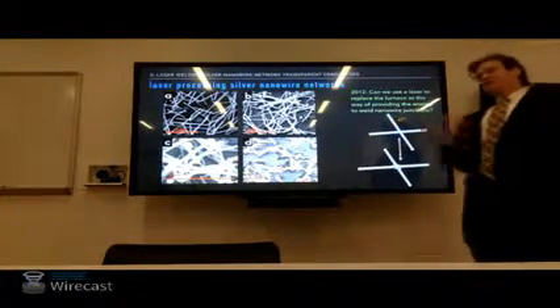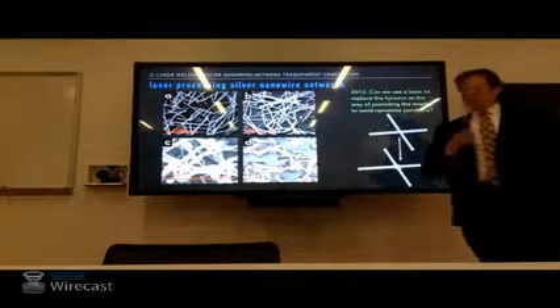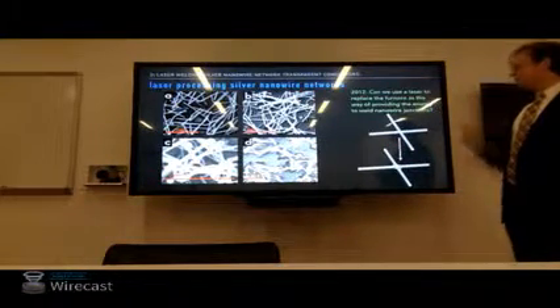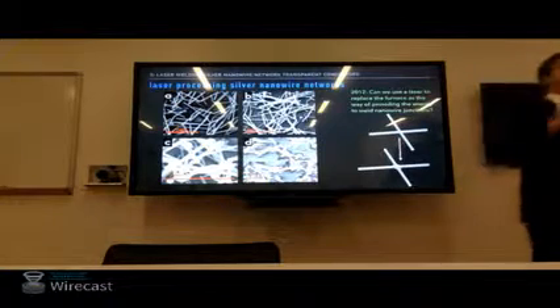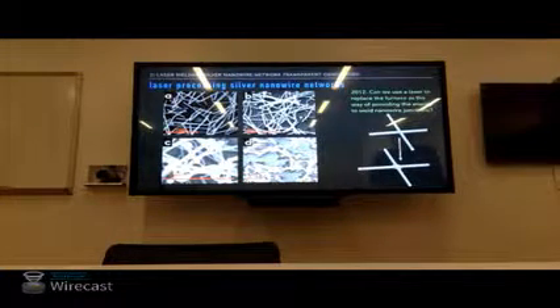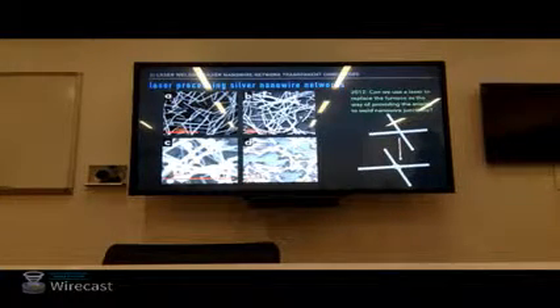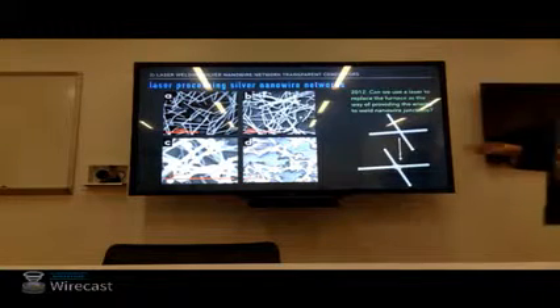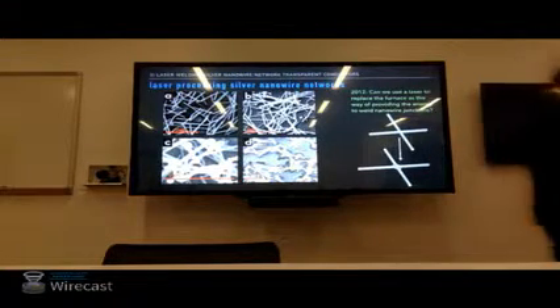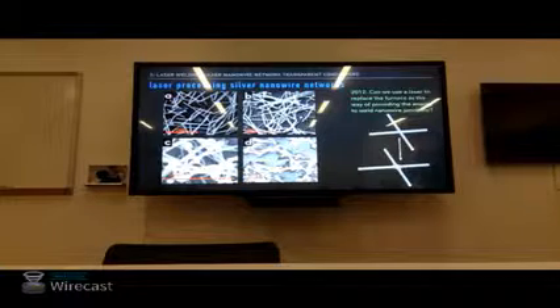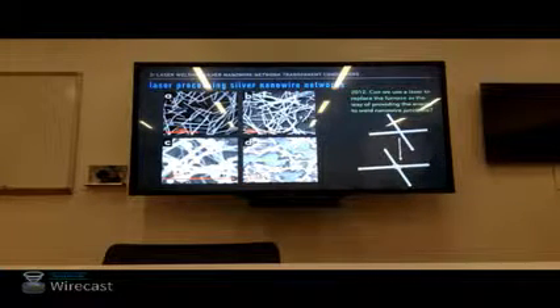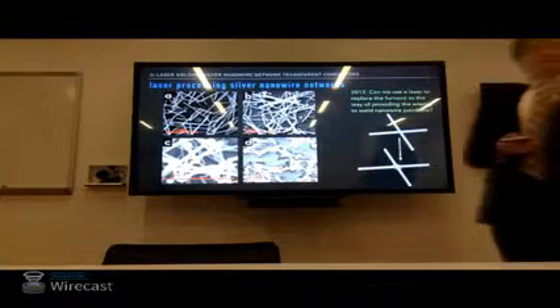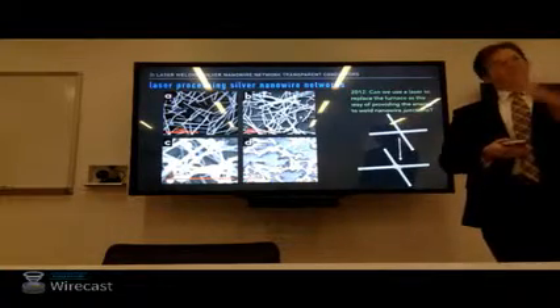The end of a nanowire is also a place where you would expect a lot of scattering, another high curvature. And of course in D, if we increase the laser energy density, or the fluence, much higher, we can definitely destroy nanowire networks. No problem doing that. So this is the direct measurement, but perhaps we're more interested in the indirect measurement, which would be measuring the sheet resistance before and after this process.